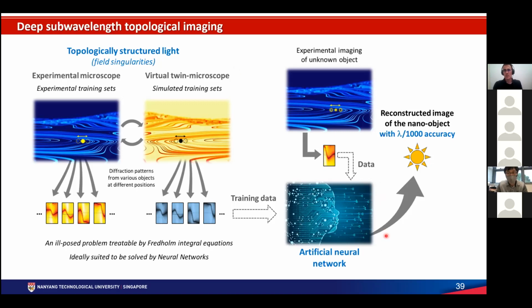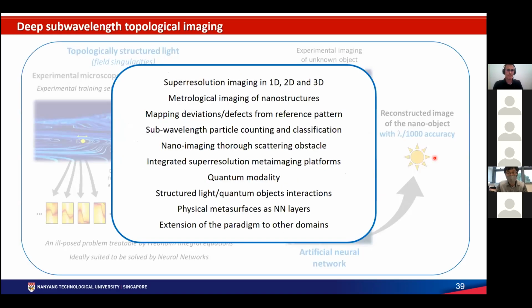Once you feed a neural network either experimental scattering patterns or virtual scattering patterns, you might be able to train it to the point that when you feed it an unknown object with an unknown shape, it will be able to reconstruct the shape with an accuracy that is of the same order as the singularity you have been illuminating the object with. So lambda over 1,000 is achievable.